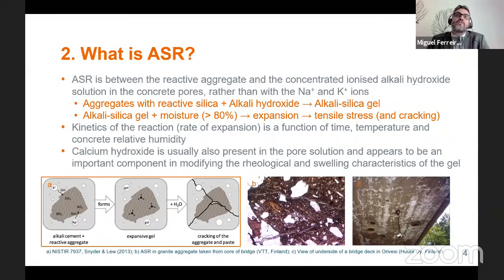And if there's enough humidity in the concrete, typically references are over 80%, then there's the formation of a viscous gel, a silicate, sodium silicate or potassium silicate, depending on the alkali ions. And this gel can move inside the concrete, and with more humidity, it can expand and exert pressures on the concrete and on the aggregate, inducing cracking within. And calcium from the portlandite in the concrete also has a special role in how it might change the viscosity of the gel and induce the precipitation of this gel as well. So concrete starts expanding, first filling up the voids of the concrete, and then when these voids are full, it starts to cause the concrete to crack, and this cracking, as you can imagine, will deteriorate the mechanical performance of the concrete.